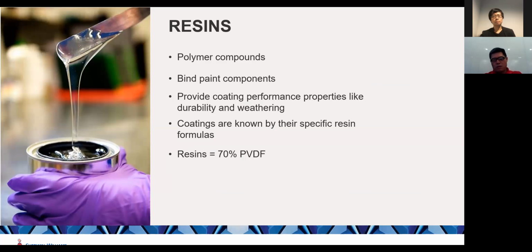And resin, as I mentioned, is one of the most important components in the coating product. We use the resin as a binder, okay, to wet the pigment, to protect the pigment as well, and also to provide the physical properties of that film so that we can fabricate the parts. During the installation, a lot of scratches may happen. So that's why we need to consider the hardness of this coating surface to meet specific requirements, okay, to avoid most of the scratches during the installation.